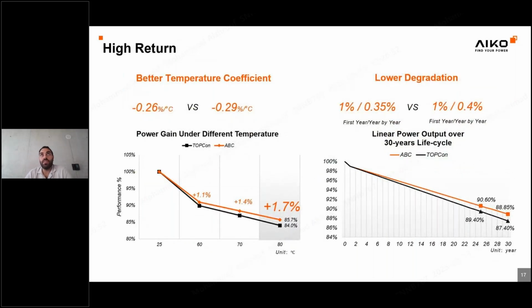Also, I would like to highlight these two features that could help the owner, let's say, of the solar project to improve his financial benefits and returns. The first one is the temperature coefficient. So the value we have in our panels is 0.26 percentage per degree, compared to TOPCon, which is 0.29 percentage per degree. Normally, you can find these coefficients on the data sheets of the panels. And normally when the panels are in operation, the temperature of the panels can easily reach 60 degrees, and this gives the ABC solution an advantage of 1.1 percentage in terms of yield and energy output.